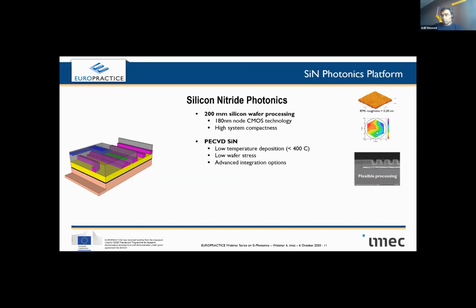So it causes low wafer stress, and it allows advanced integration options. As you can see in this case, there is a grating coupler. This is the silicon nitride layer, and beneath that a layer of metal was fabricated. That means light coming from the top can actually be reflected back into the couplers, increasing coupler efficiency. Again, unfortunately, this metal mirror beneath is not yet available in MPW offers, but it is part of the platform, and that shows the advantage of PECVD silicon nitride.